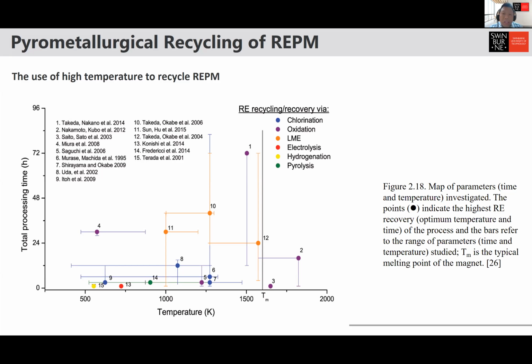So as you can see from here, for example, the oxidation tends to take quite a significant time, right? Because later I will also show an example of that process. But it also takes a high temperature to produce these oxides. For example, this one and this one are actually beyond the melting point. So we actually melt the NdFeB, and we form oxides of these rare earth elements, rare earth oxide mixed with other elements in there.